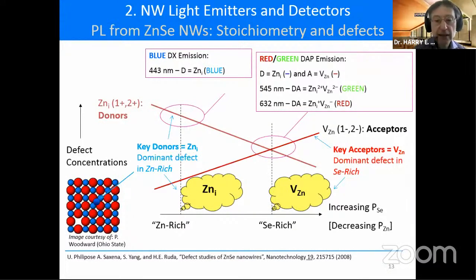Which means that if we're looking at a strongly zinc-rich condition on the left of this diagram, then we have quenched off the zinc vacancy concentration, and really the only native defects in the system of note are the zinc interstitials. And that's why the donor-bound exciton emission, involving just that donor, the zinc interstitial donor, was responsible for the blue emission.